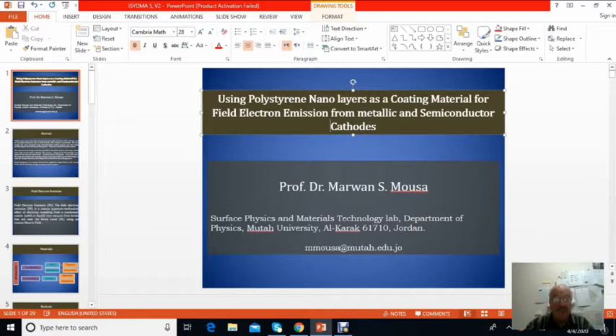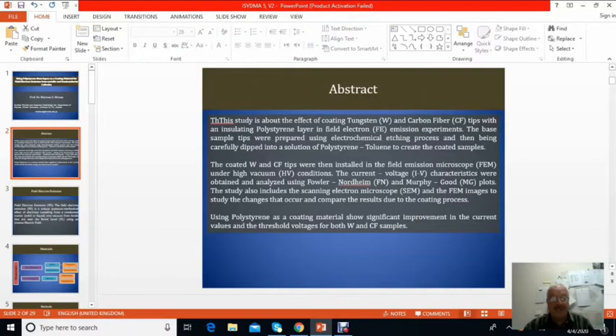Today, we are presenting work using polystyrene nanolayers to coat both tungsten metal and carbon fiber, which we can call semiconductor cathodes. This study is about the effect of the coating of both types, tungsten and carbon fiber tips, with a polystyrene layer, and applying the field emission techniques for measurements. The base sample tips were prepared using the normal procedure of electrochemical etching.